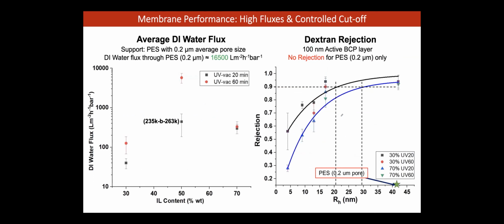But we were really interested in developing some real membranes. So actually we partnered with Qatar University and with ConocoPhillips. And we did a whole bunch of studies for oil water separation, just showing you that this thing about optimization of pore density with pore size is not trivial. If you look at just the red dots, as the ionic liquid content increases, it goes through a maxima and then comes down, right? This is in terms of the flux. So the flux goes through a maximum and comes down.